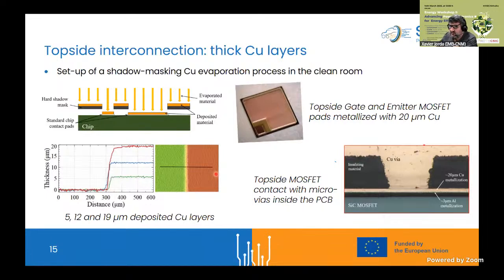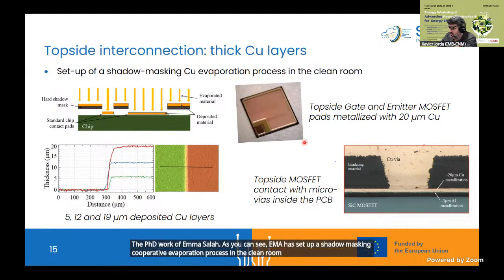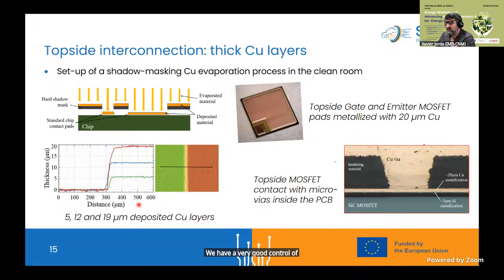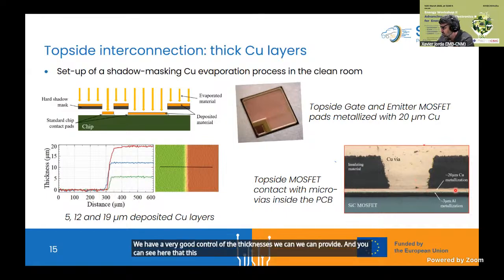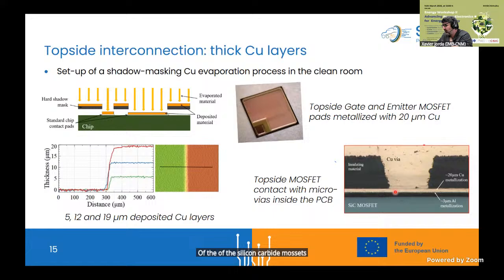As you can see, Emma has set up a shadow masking copper evaporation process in the clean room, where we have been able to obtain these thick layers on top of the dies. We have a very good control of the thicknesses we can provide, and you can see here that this top side copper layer is required to obtain the interconnection of the silicon carbide MOSFETs with the tracks of the PCB, okay, in the chip embedding implementation.